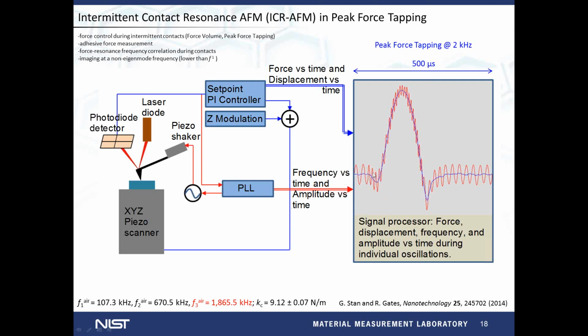Outside of contact, the resonance frequency is that of the eigenmode of the cantilever used. In this example it was the third eigenmode of the cantilever. Once we bring the probe into contact, we have a shift to higher and higher frequencies until the peak force, and then the resonance frequency decreases, and out of contact it comes back to the free eigenmode frequency. What I want to point out is that we apply these two modulations to the tip-sample contact through two separate paths. The blue one is the PeakForce modulation, applied on the Z piezo scanner of the AFM. The PLL modulation was applied on the piezo shaker of the AFM, to minimize cross-talk.